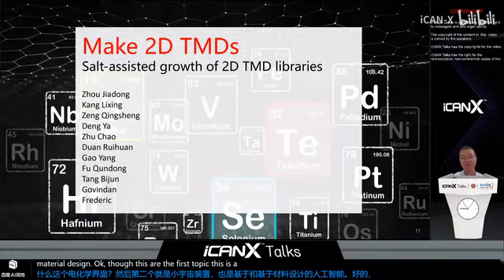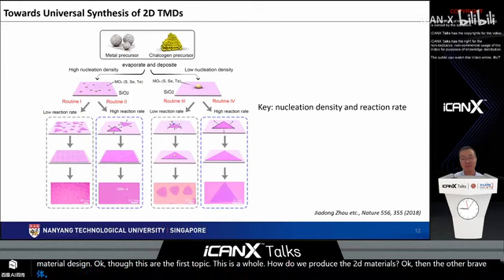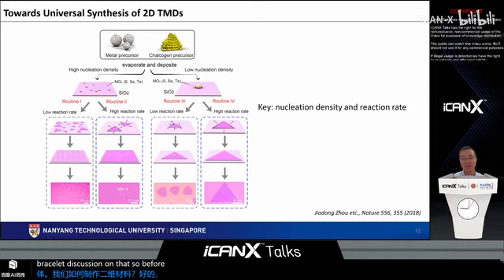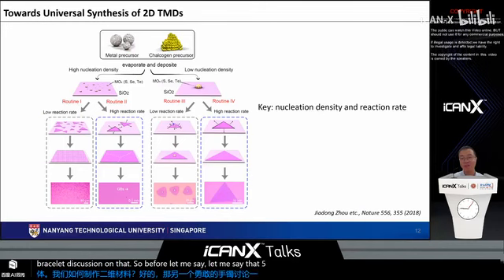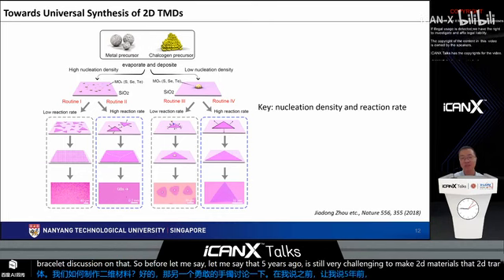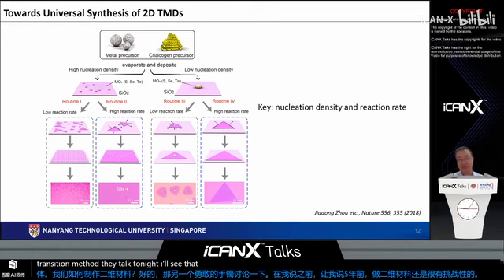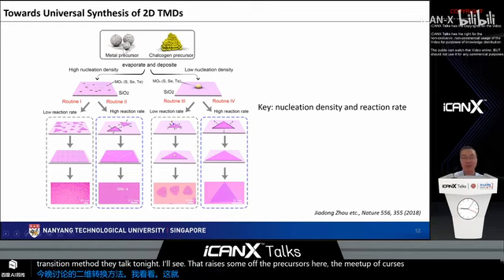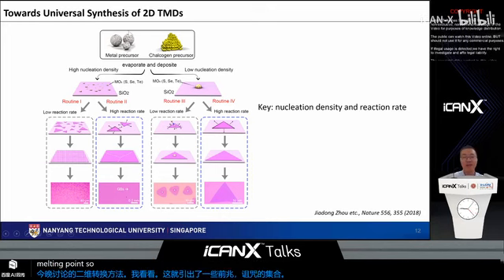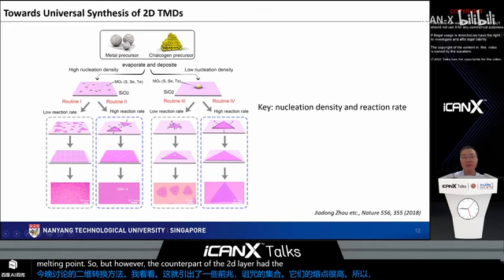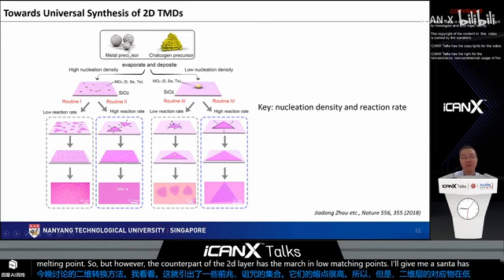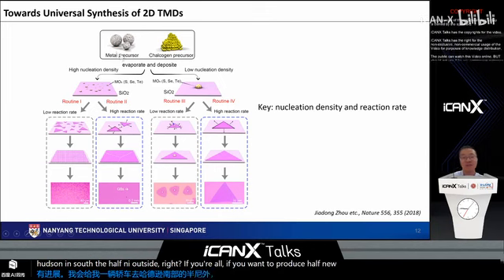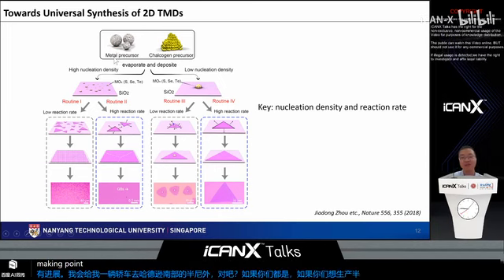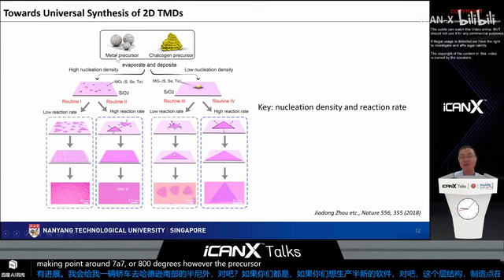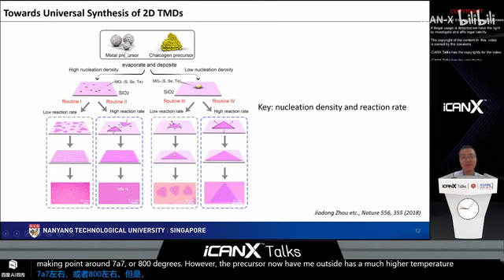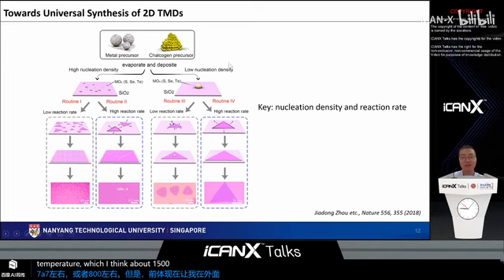Okay, so these are the first topic. This is how we produce the 2D materials. This is just a brief discussion on that. Before, let's say 5 years ago, it was still very challenging to make 2D transition metal dichalcogenides. I think the reason is that some of the metal precursors have a pretty high melting point. However, the counterpart, the 2D layer, has a much lower melting point. I'll give you an example: hafnium oxide. If we want to produce hafnium sulfide or hafnium telluride, this layer structure has a melting point around 700 or 800 degrees. However, the precursor, hafnium oxide, has a much higher melting temperature, which I think is above 1,500 degrees. So this is the main challenge.